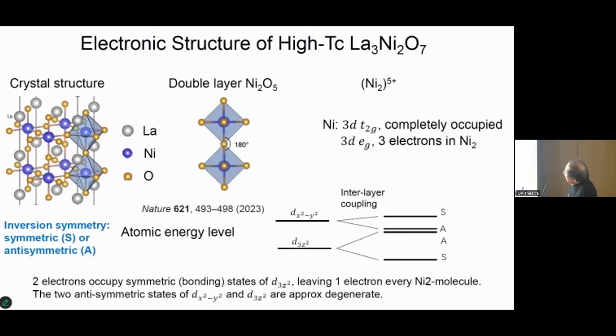So this is the electronic structure again. If I do this analysis, then I have these two relevant eg orbitals, with the dz square lower and the dx square minus y square slightly above. Remember that nickel is actually 2.5 plus... for each one. Here, for the 2 nickel molecule, I have 3 electrons on this eg state, for 2 nickel sites.